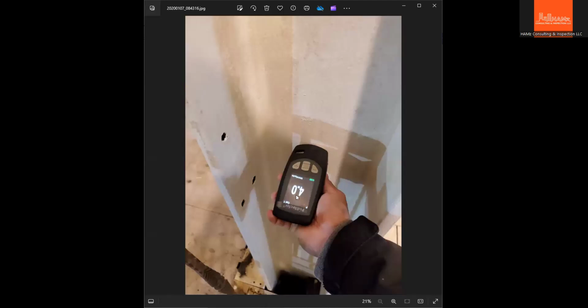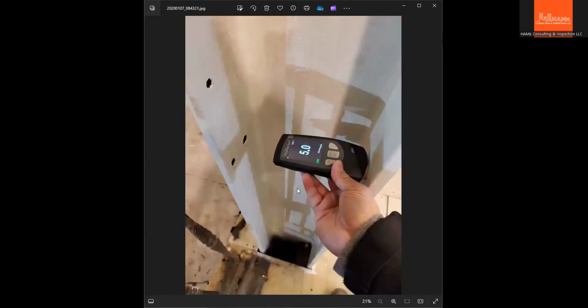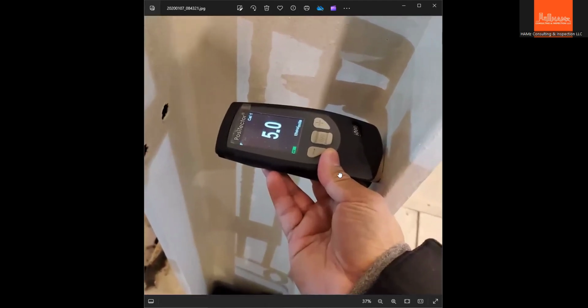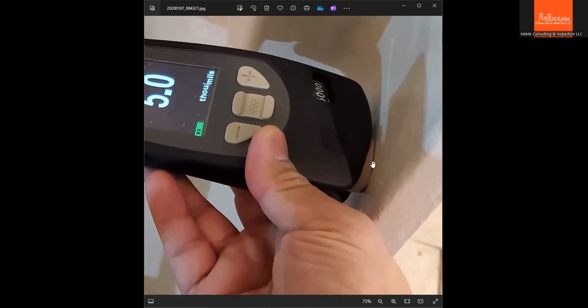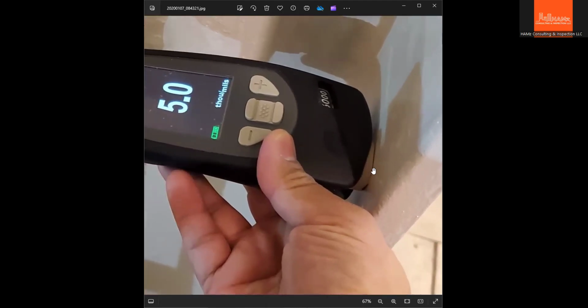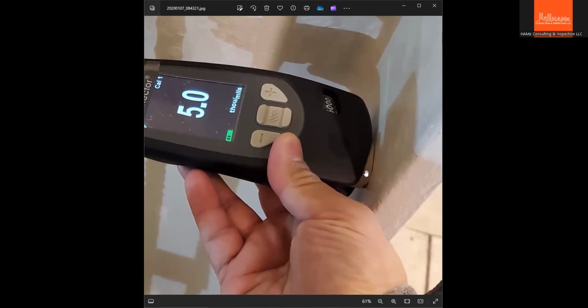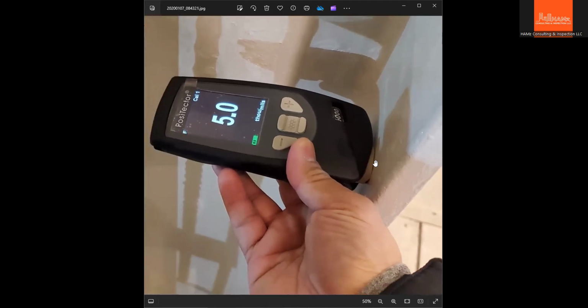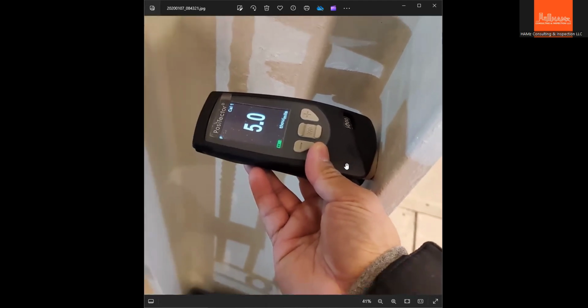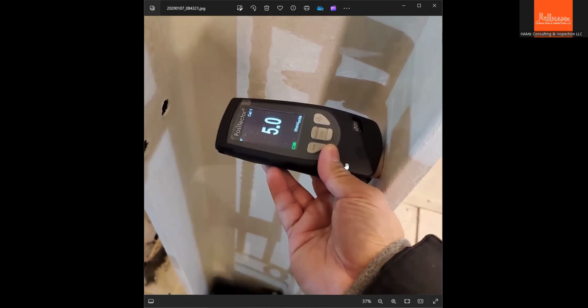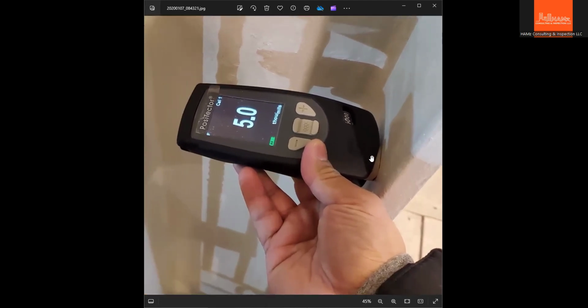Another web is 0.4 mils only. And the inner surface of the other side of the flange, as you can see. So this is the probe. The probe will circle about half an inch around that point. On that point, you're gonna circle it in a half-inch area only to get the average reading. So I usually do 5 readings in each point like this.